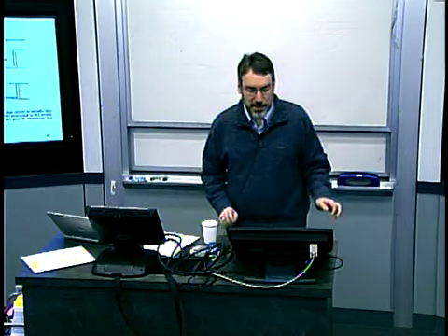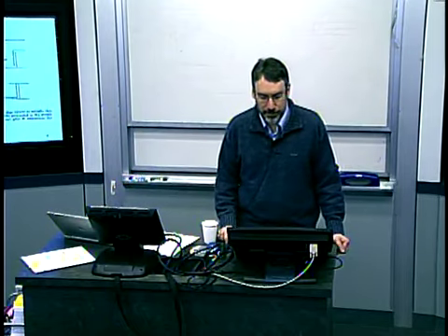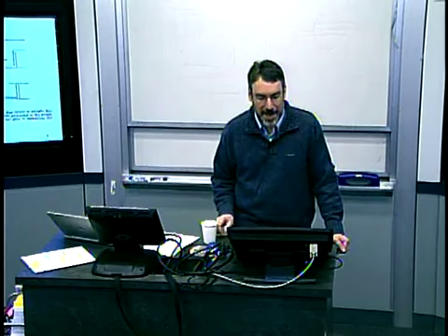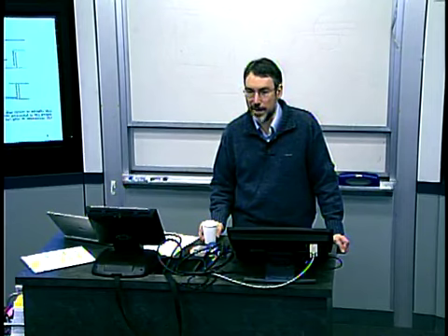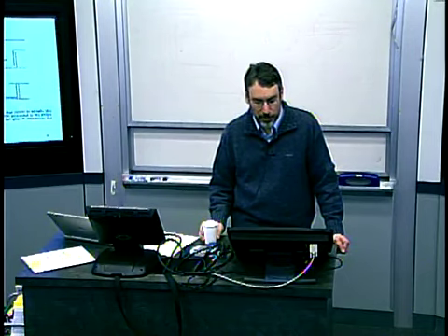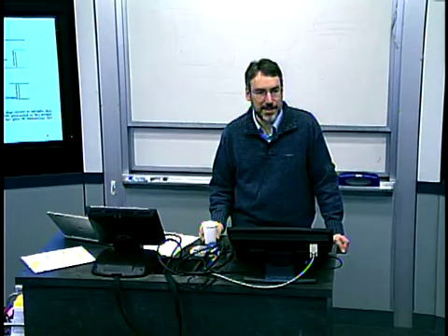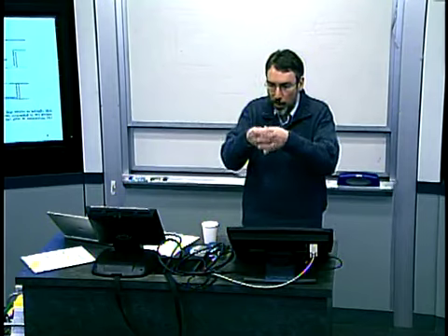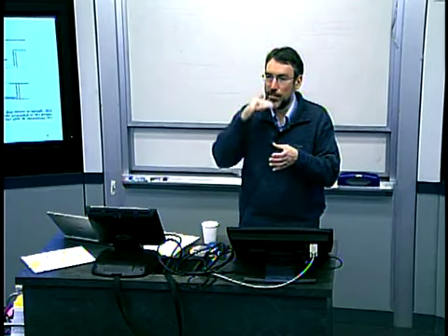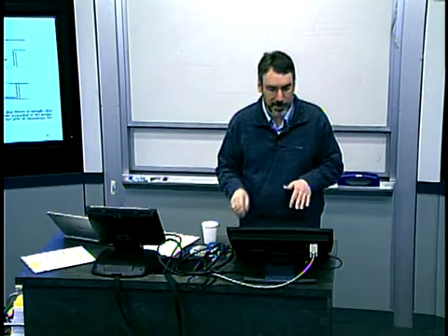So let me talk a little bit about tungsten, and in particular tungsten plugs. So tungsten here is generally used as a conductor in semiconductor fabrication. It's not a great conductor, meaning it's often a little bit higher resistivity than other metals like aluminum or now copper. However, it continues to be heavily used for contacts and plugs. So contacts are the holes that are drilled between or into an insulating layer from the first level of metal down to the underlying silicon.